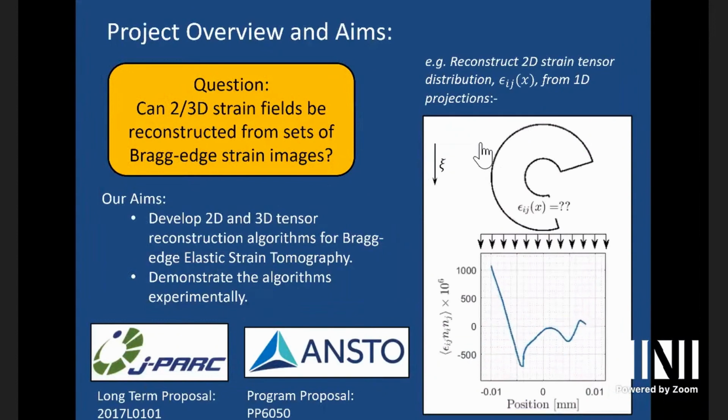And the point is, the other technique, diffraction, we can just probe points. We can measure whatever we want, and each measurement will tell us what its strain is at that particular point. In the transmission mode, we get kind of blurred along the line, and so we see a tomography problem, right? There's a natural tomography problem here.